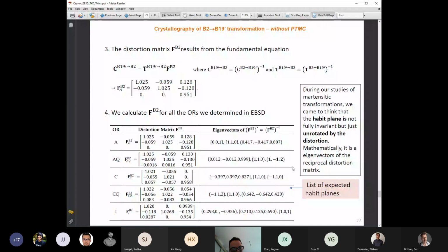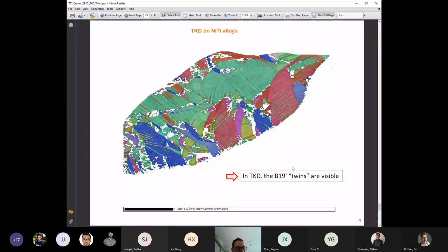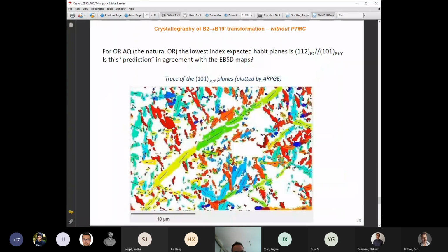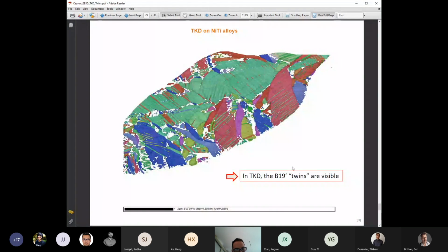Yeah, in the title there was the word TKD. It's also to tell you that in the previous EBSD we do not see the fine structure. We see the martensite, but we do not see what is called the twins inside the twins. We do not see the twins inside the martensite, whereas we know from TEM that they exist. And if you use the same sample and you do TKD on it, then we see the twins inside the twins. So TKD is really a very good complement to EBSD to look at the finer structure inside the martensite.